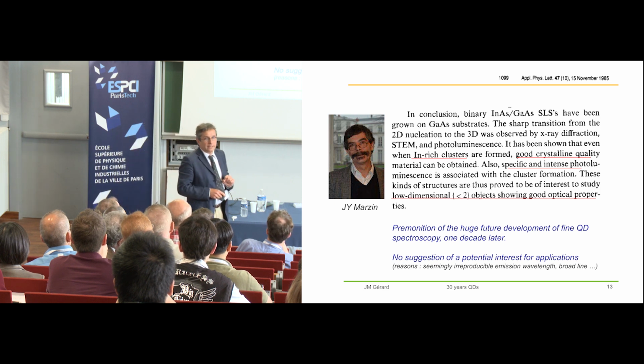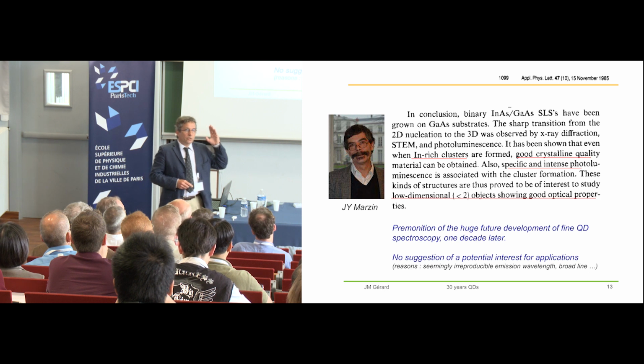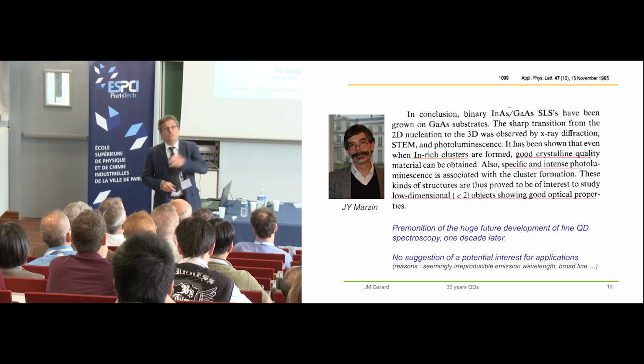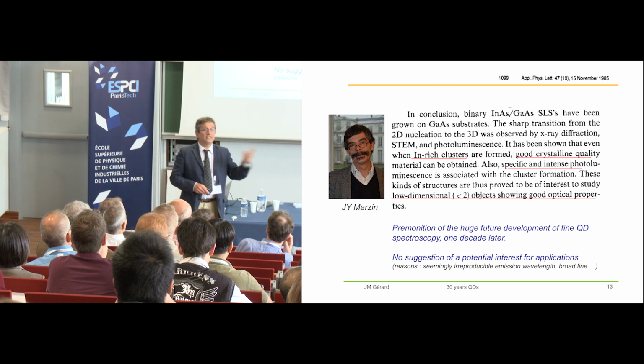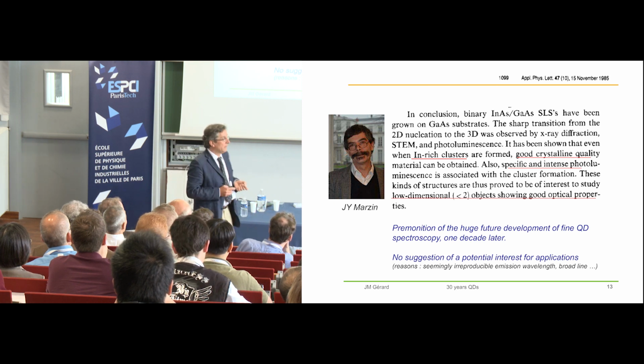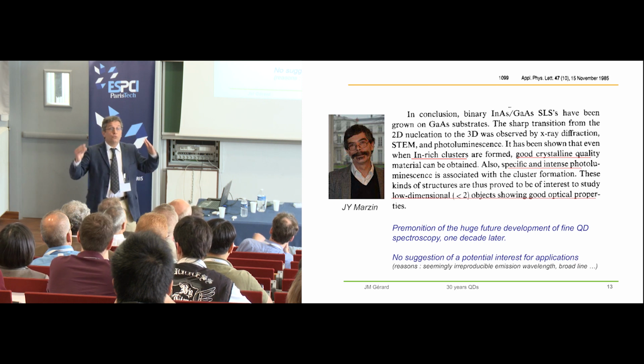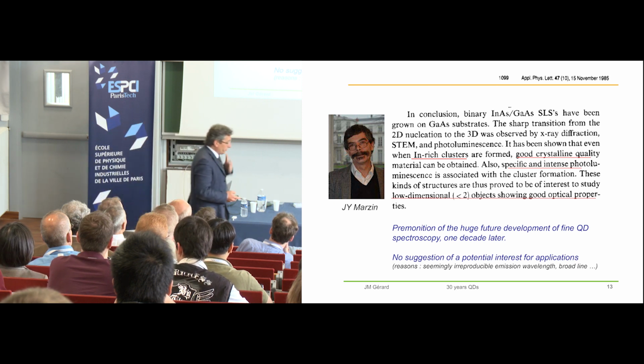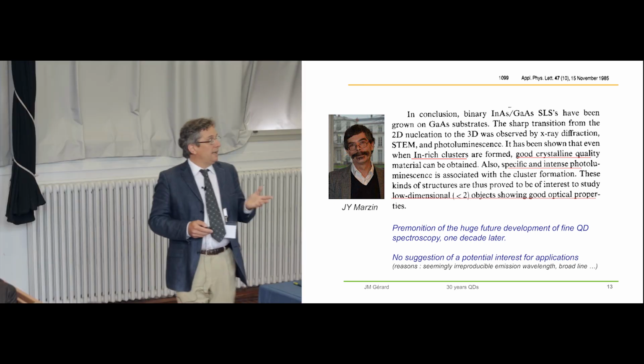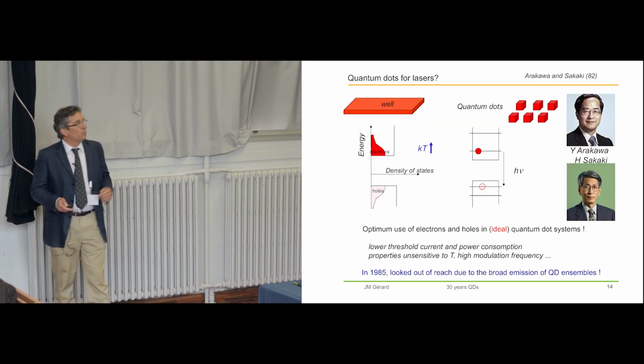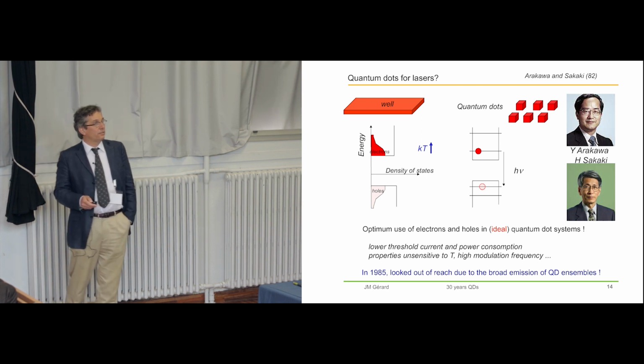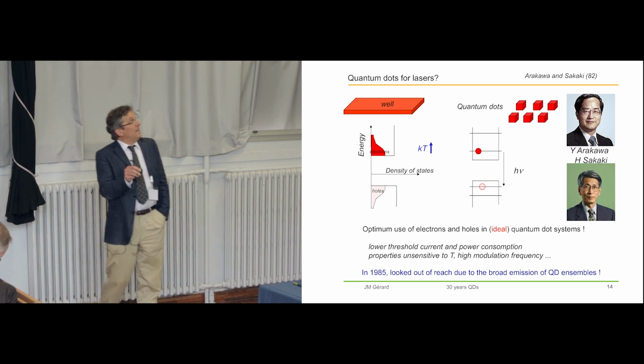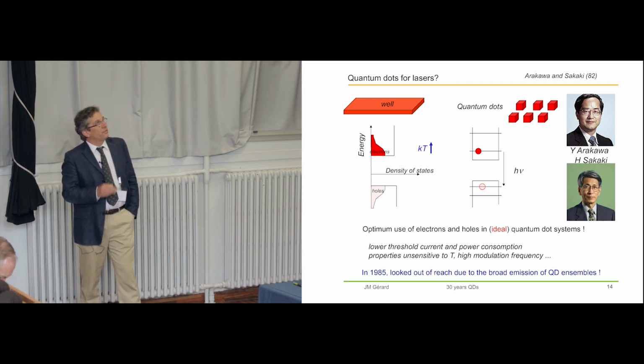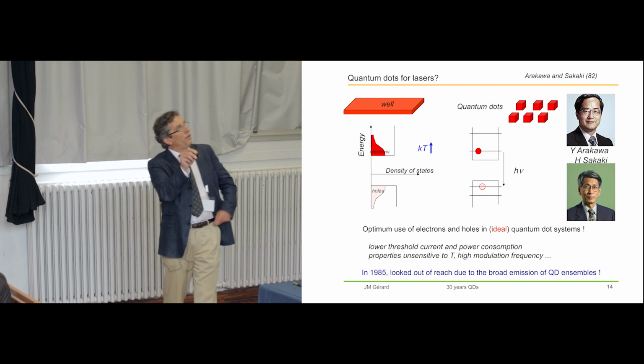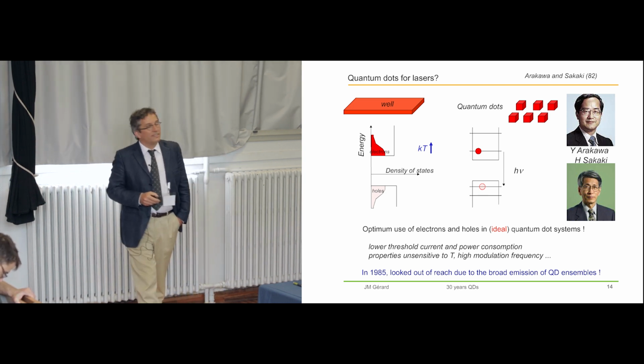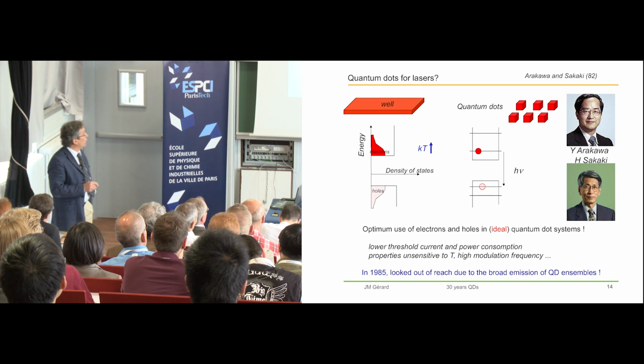And there are two reasons for that. First of all, when the quantum dot samples were grown, the wavelength was not always the same. It did not look reproducible. Second, the line was really very broad. So it was difficult to say, okay, such quantum dot arrays will have applications in the field of lasers. And if I say that, it's because, in fact, quantum dots for lasers had been proposed 3 years before by Arakawa and Sakaki.